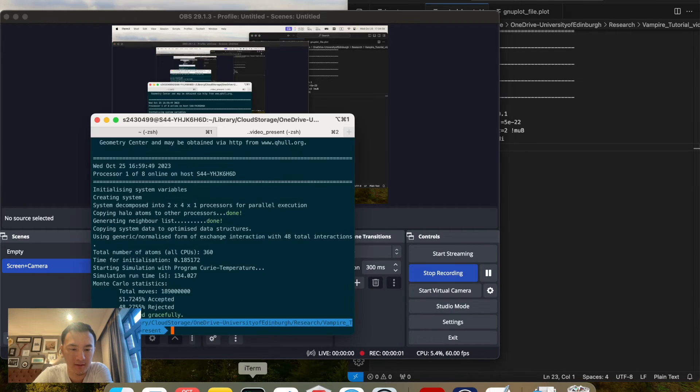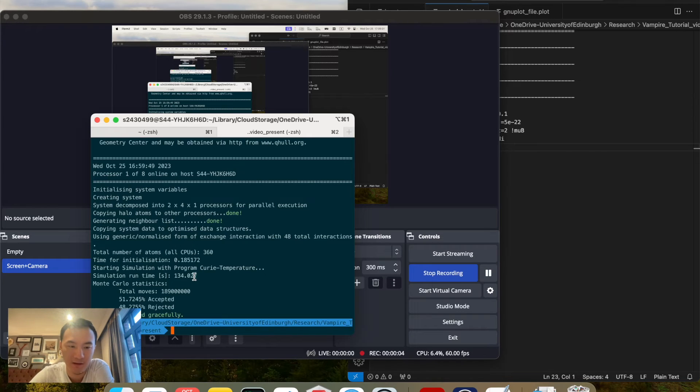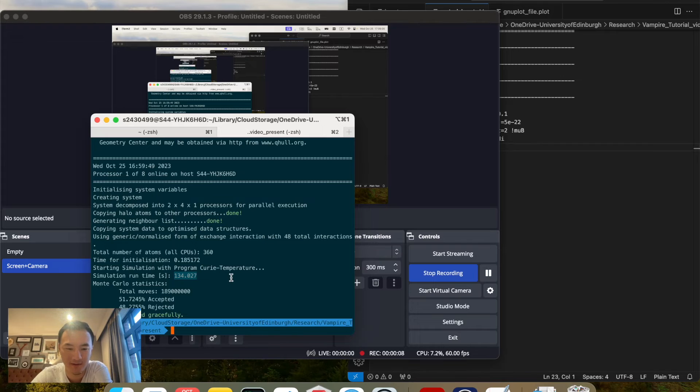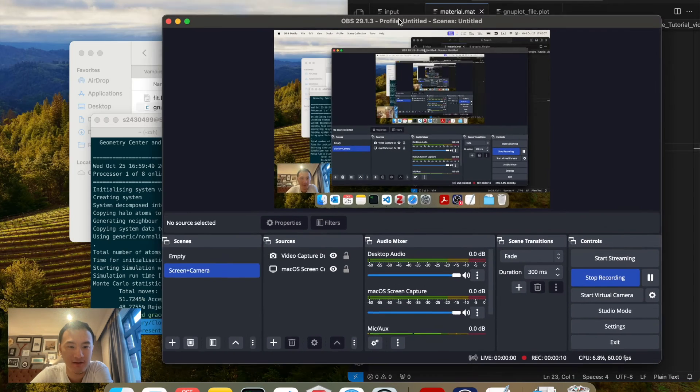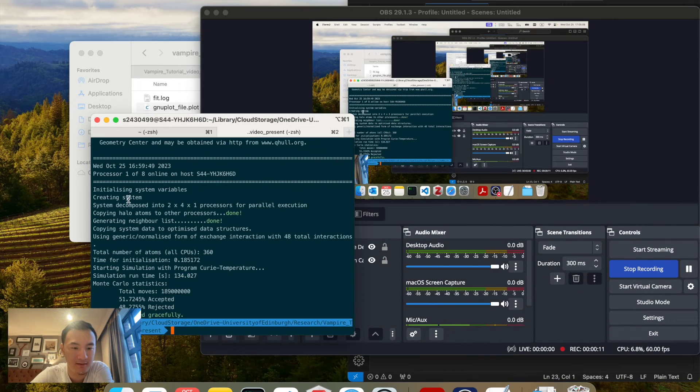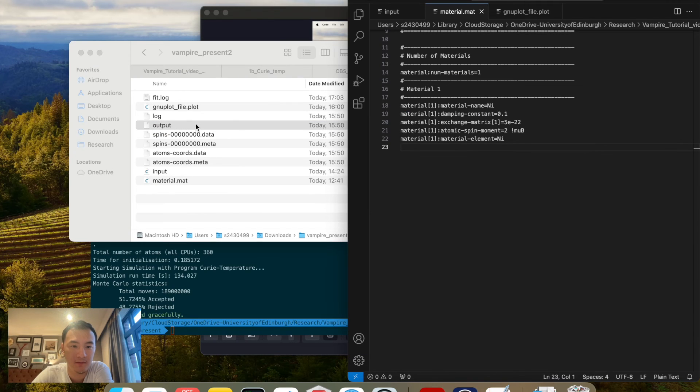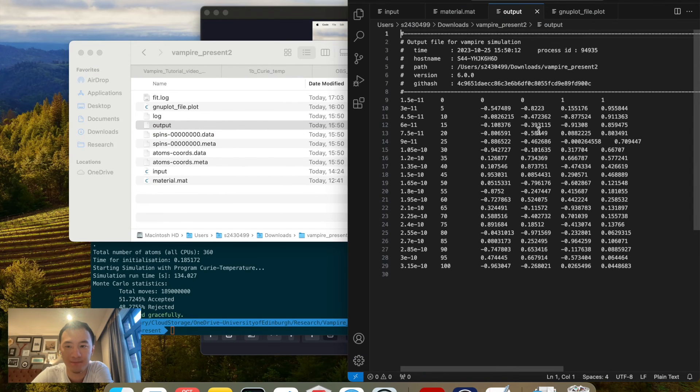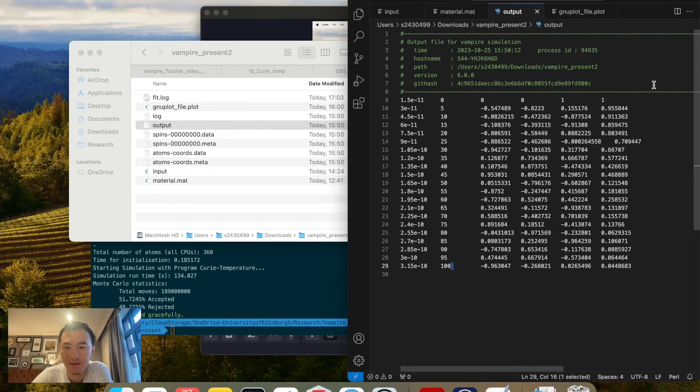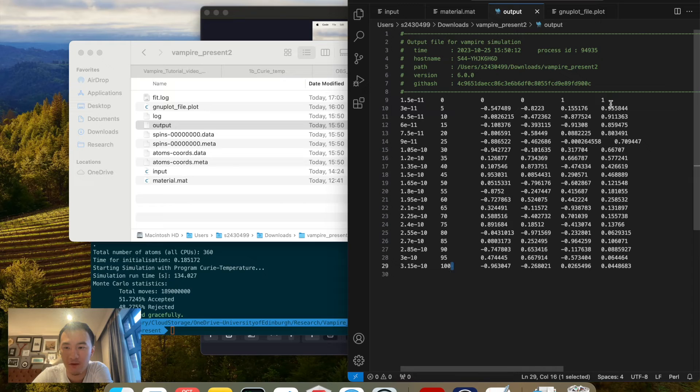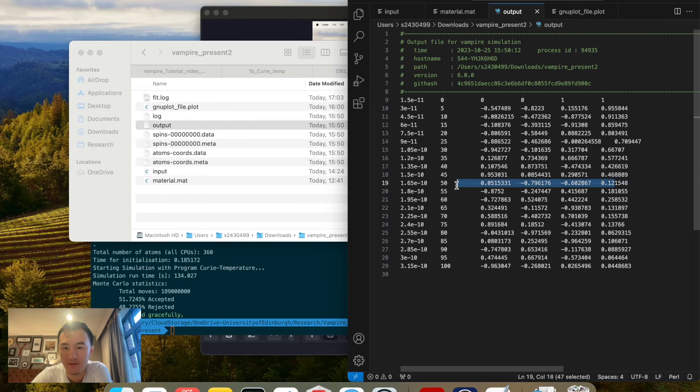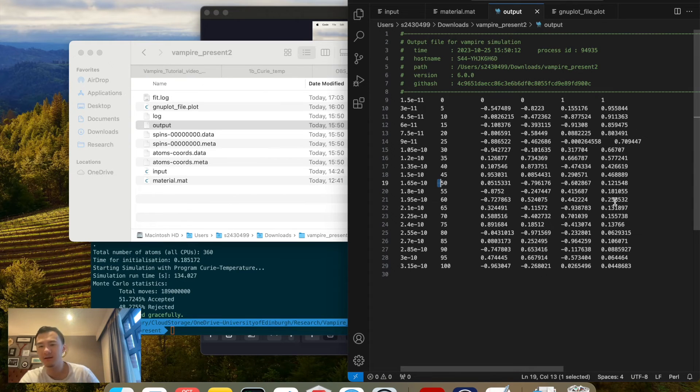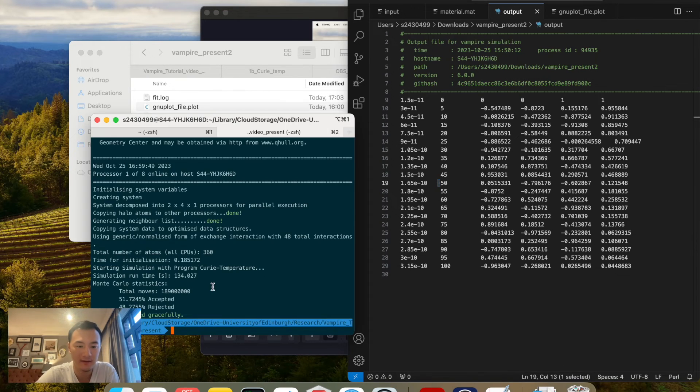Okay, the simulation has ended. It took longer than I expected because I had OBS open in my background. But now it has finished. Let us open the output file. We run from 5 to 100K, and magnetization started from 1 and it reduces to about 0.5. That's the lowest point, and then it bounces a little bit back up.